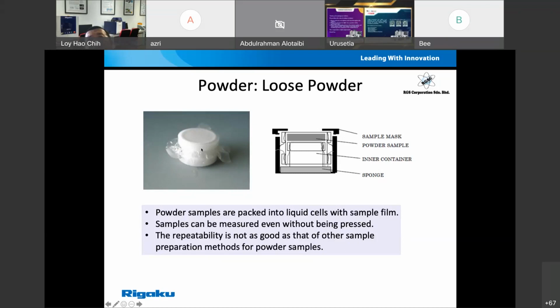Because when X-rays, as Kelvin mentioned earlier, try to come out from the samples, they need to get through the films. When they get through the films, a lot of the energy is absorbed by the films, especially when you try to measure light elements, such as what Kelvin mentioned, anything lighter than fluorine, nitrogen, oxygen, or even fluorine. And because the films are made of plastics, the plastic itself already contains a high amount of carbon, oxygen, and nitrogen. So this will also give you errors, and your light element XRF energies will also be absorbed by the films. So at the end of the day, this will give you a wrong measurement result.